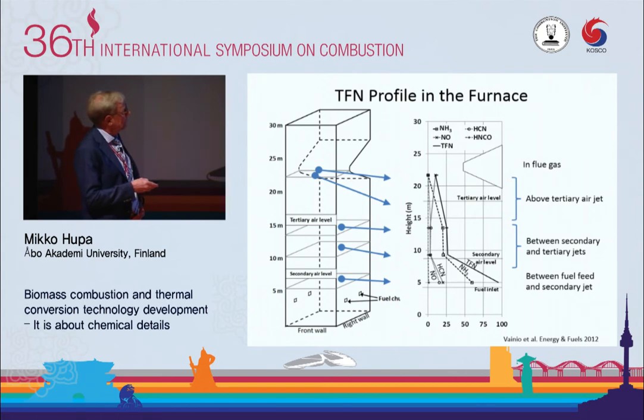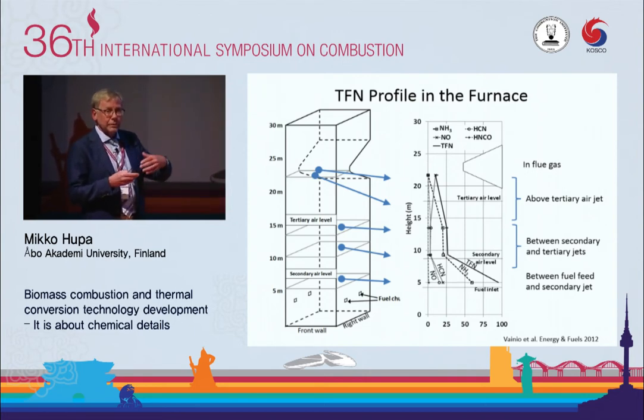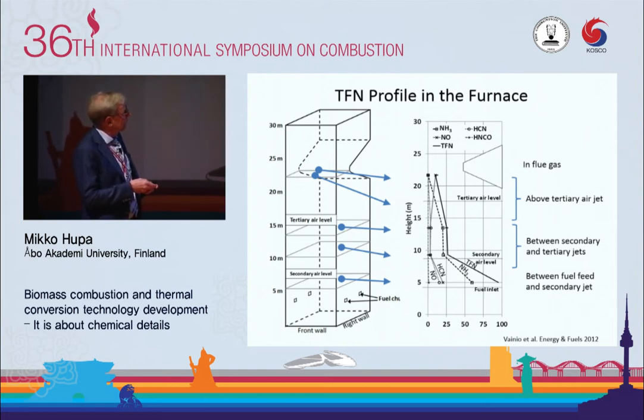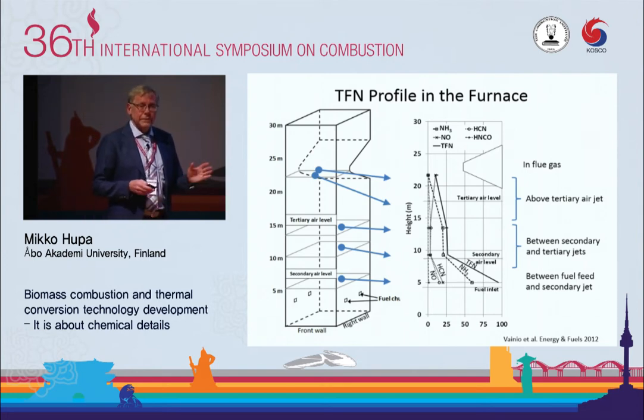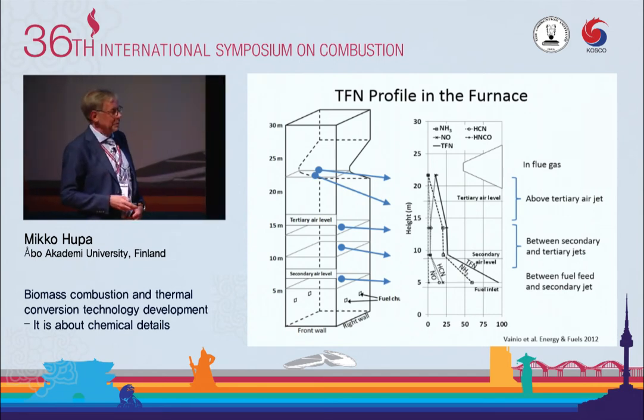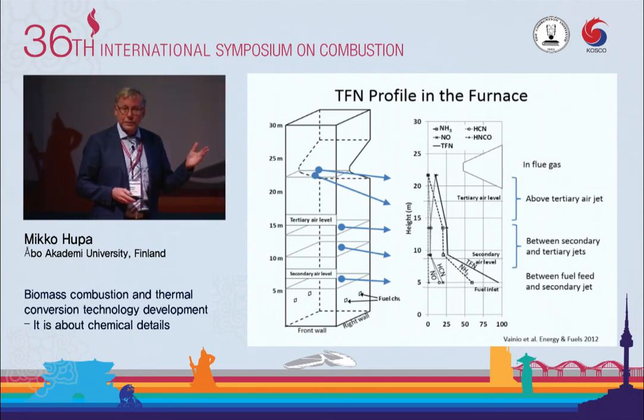But the more interesting surprise was that there was an extremely heavy reduction of the fixed nitrogen along the furnace. So in the lower furnace, we had almost all fuel nitrogen converted to fixed nitrogen. But then when we went up and made measurements in different locations, here are those points collected. The ammonia, hydrogen cyanide, NO contents went steeply down here, and then they stayed a while unchanged, and then they continued going down, and finally were only about 10% of what was original. This is a very good reduction. On the other hand, these boilers were not built for NOx reduction.